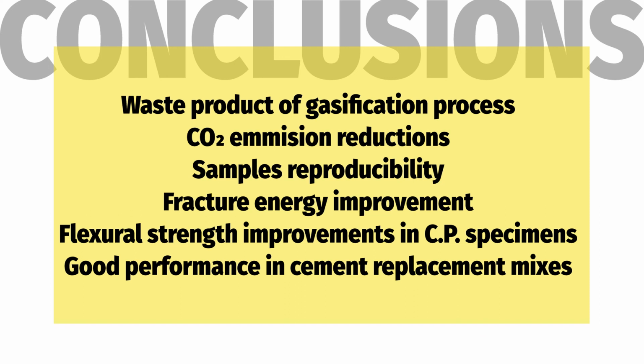waste material, and using a waste material implies a reduction in carbon dioxide emissions, thanks to the gasification process. With respect to the cement paste specimens evaluated, there was a significant increase in fracture energy, which translates into an increase in the ductility of a fragile material. In addition, there was an increase in flexural strength in cement paste and a good performance in cases where the cement was replaced with biochar.